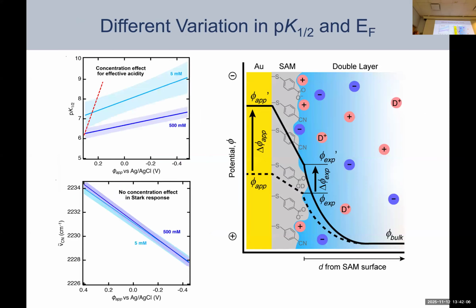So we went through a whole detailed analysis of this system, and I won't bore you with the details, but suffice it to say that we see some really different concentration effects in terms of effective acidity, or pK1/2. This red line is our expectation of a 59 millivolt per decade change. And in light blue and dark blue, this is our observation, either in less concentrated electrolyte or more concentrated electrolyte. So you see the expectation is very different from the observation.